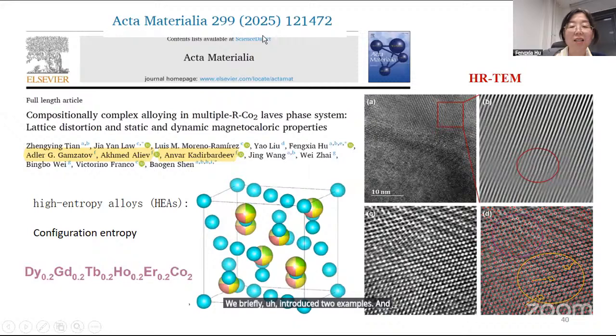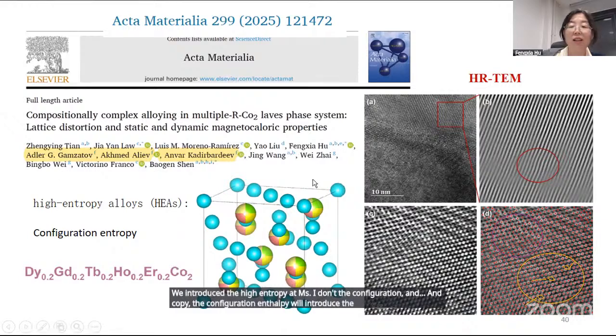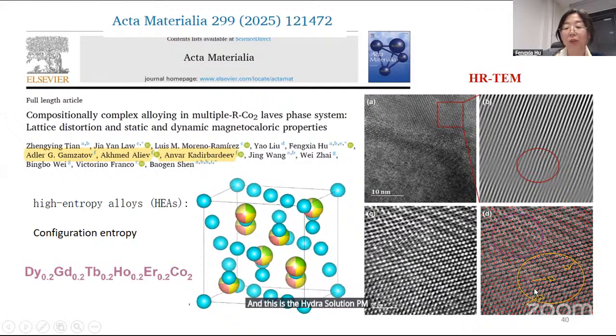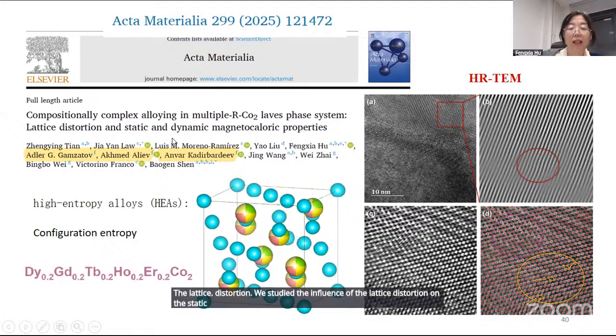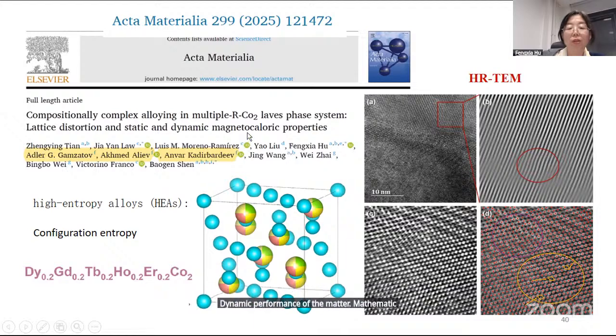This example was just published this year, and this work focuses on the high entropy alloys for the materials of R-cobalt. In the R side, we introduce the high entropy. That means I introduce the configuration entropy. The configuration entropy will introduce the lattice distortion. And this is the high resolution TEM result. We can see the lattice distortion. We studied the influence of the lattice distortion on the static and the dynamic performance of the magnetocaloric effect.